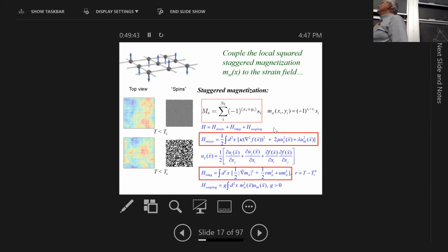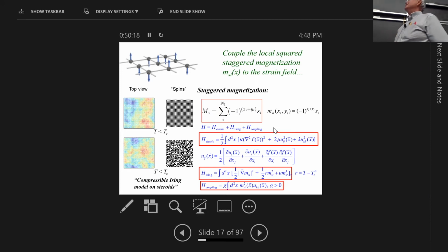So we have this set of critical degrees of freedom, it's always critical. This set becomes critical when the mass goes away, the quadratic term in the Landau expansion. And then the most interesting part, in my view, is this coupling between the 2 degrees of freedom. It's a compressional coupling that says that when you have a staggered Ising order parameter, that's going to couple to the local dilation of this strain matrix. And it turns out that this compressible Ising model on steroids, which is what I like to call it, to distinguish it from the compressible Ising models that were studied before we allowed escape into the 3rd dimension.